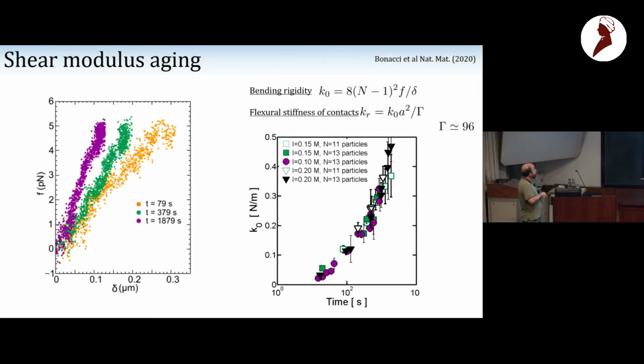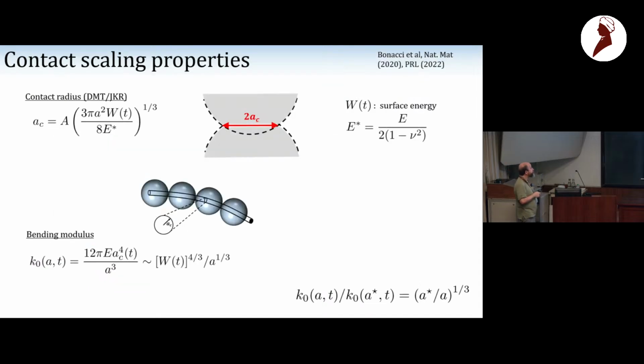So now you see here the force deflection curves measured at different times, and so we do see that there is an evolution of the stiffness of the contact. And so now we extract the bending rigidity of contacts from different experiments with different ionic forces, different numbers of particles. And so you see that generically we measure an evolution of the bending stiffness as a function of time, right? So the contacts stiffen with time. Okay, so we can go through the theory.